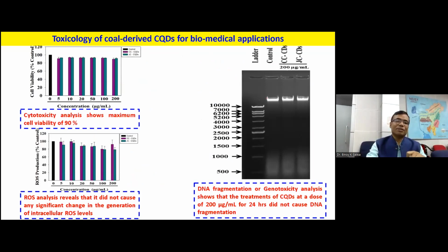If we go for applications, then definitely application scientists will ask whether it is toxic, whether it will affect the DNA or the gene, because for biomedical applications toxicity is most important. So we performed cell toxicity and cell biology studies, and also DNA fragmentation. We found excellent results: there was no cell damage or DNA fragmentation up to 24 hours of application at a maximum concentration of 200 microgram per ml. So it is an absolutely non-toxic material made from coal, like other quantum dots made from very pure sources.